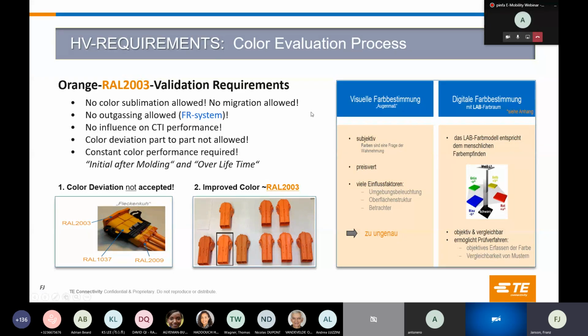So requirements have been established, like no color sublimation, no migration, and outgassing, if possible, not. We made some measurements on the CTI influence from the colors. We found out that in some cases, depending on the pigments which have been selected, we do not have a real influence. In some cases, we have a drop of 50 volts or even more, depending on the color pigments and their chemical structure. The color deviation part to part, as already mentioned, is not allowed. Therefore, our intention was to have one solution in place, which is a pre-colored material. And at the end, we had to do some validation in our molding site, and also check the color performance over lifetime on the part.